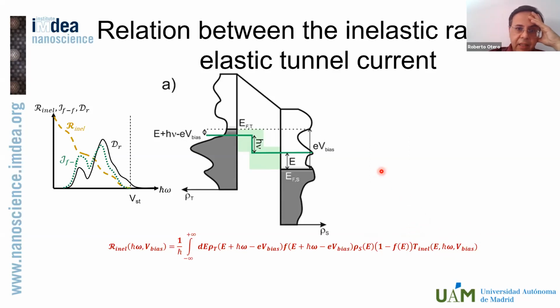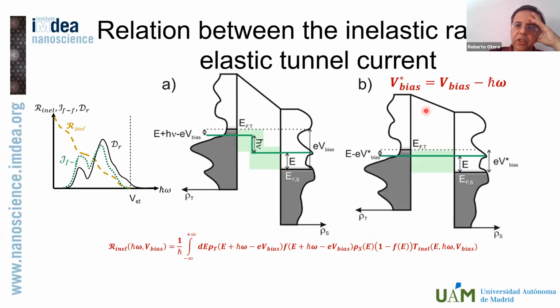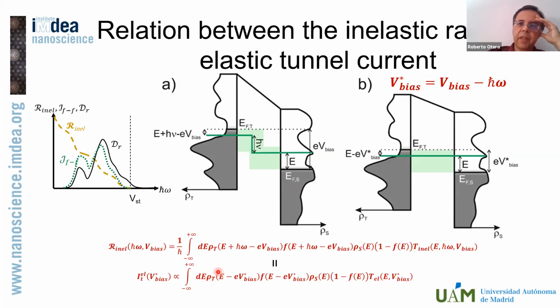Now, the interesting part is that if we consider a hypothetical situation in which we modify the actual bias voltage that we apply by subtracting the photon energy, then we are aligning the initial and the final states in the tunnel process. That would make my tunnel process switch from inelastic to elastic. And the nice thing about elastic processes is that we know how to calculate them. Once again, it's just the density of states times the Fermi occupancy, the density of states times the Fermi occupancy, and some weight in between. If you compare those two contributions, you see that they are exactly the same if your V bias star corresponds to V bias minus the photon energy.